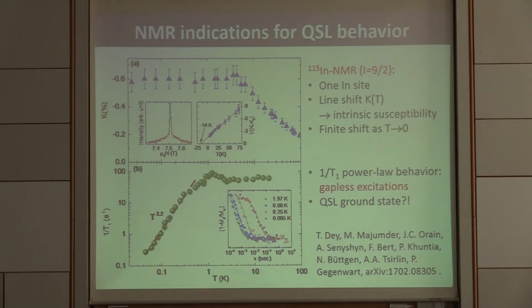We also did NMR experiments in Augsburg with our colleagues, and first here we show the shift of the indium NMR spectra with temperature, and that shift represents the intrinsic susceptibility of the material, and it's very consistent with the bulk susceptibility. We again get a Curie-Weiss-like behavior with a Weiss temperature of minus 10 Kelvin, and interestingly the shift remains finite upon cooling to very low temperatures, down to well below 1 Kelvin. And also we looked at the spin-lattice relaxation rate, which is shown here on a double log temperature scale, and at temperatures below 1 Kelvin we see a power law behavior, a signature typically associated with a quantum spin liquid with gapless excitations.